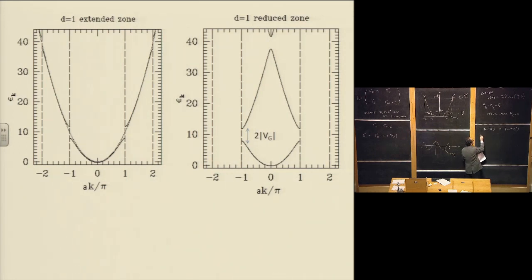So in real space, if I think about x, k representations of these kets, these things are e to the i pi over a x and e to the minus i pi over a x. I'll use that notation. If we then diagonalize this Hamiltonian in this space, we'll get our two eigenfunctions. Our psi plus will be e to the i pi over a x plus e to the minus i pi over a x, and its energy E plus is E sub pi over a naught plus V twiddle. And the other eigenstate, psi minus, is e to the i pi over a x minus e to the minus i pi over a x, and its energy E minus is E naught pi over a minus V twiddle.